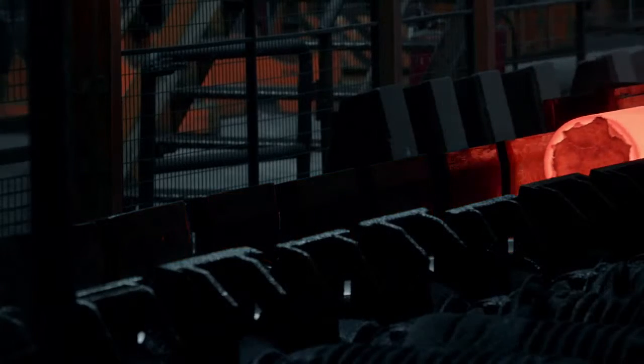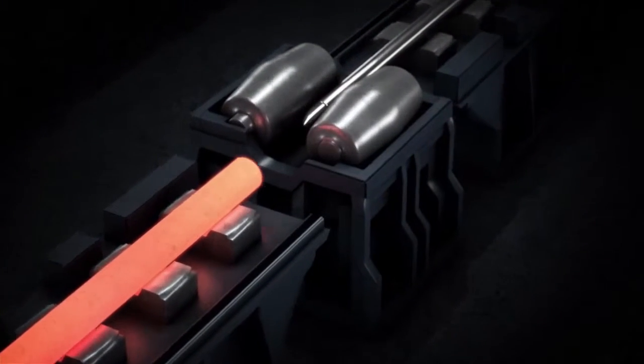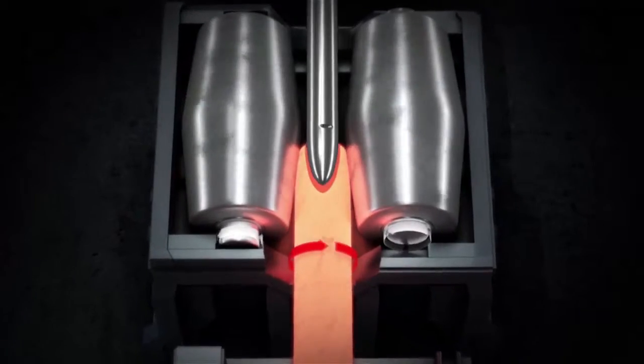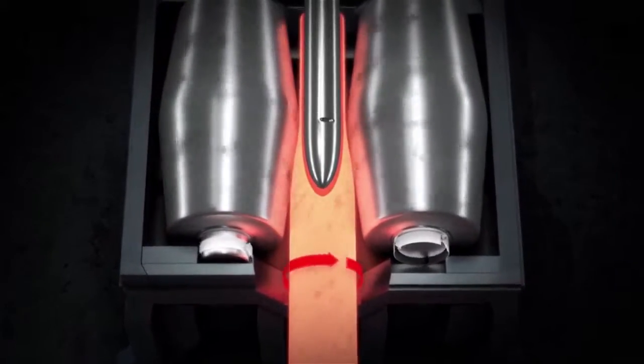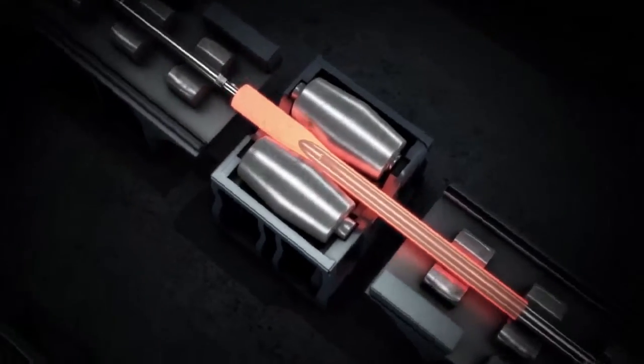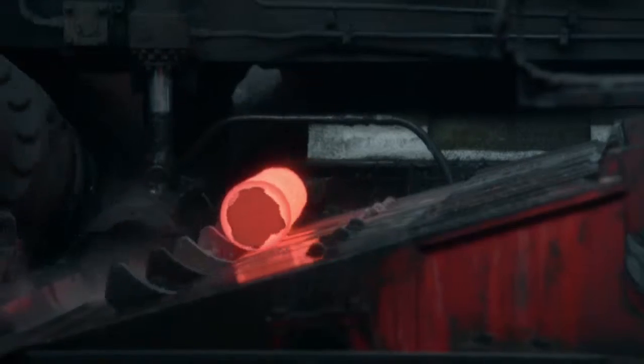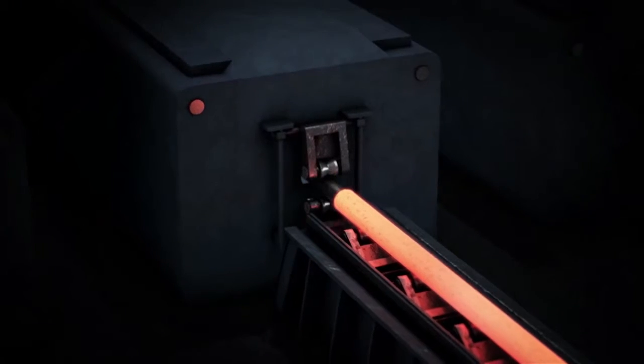The rotary piercing process transforms the hot billet into a hollow shell. During this process, the material advances on a helicoidal pattern driven by 2 rollers. The rolls generate internal tension and a cavity forms in the billet. The piercing plug then enters this cavity. The resulting hollow shell is a rough, short tube with a large diameter and thick wall.